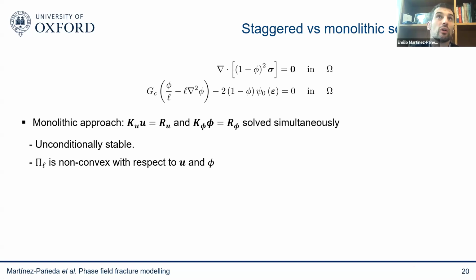One is through what we call a monolithic approach. So we solve at the same time for the displacement field and for the phase field. And this is good because it's unconditionally stable. So you can run implicit simulations with very large time increments. The problem is that this regularized functional is non-convex with respect to the displacement field and the phase field. So convergence can be a bit tricky. And this is the usual problem for all kind of non-local continuum damage mechanics models.